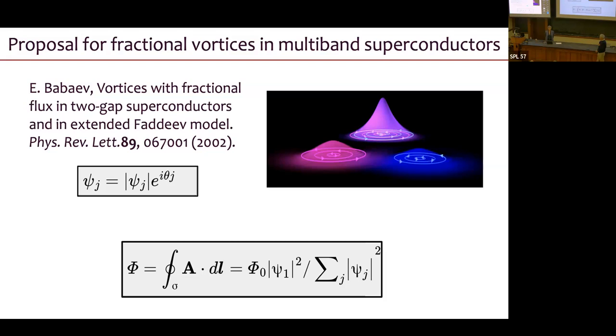And actually, he sees these very beautiful six-fold symmetry. I would call them more like snowflakes than starfish. But he sees these very beautiful six-fold symmetric vortex patterns associated with a combination of the vortex lattice structure and the band structure of the material that he was looking in, niobium diselenide. I am not aware of people seeing that kind of structure in magnetic imaging of vortices.